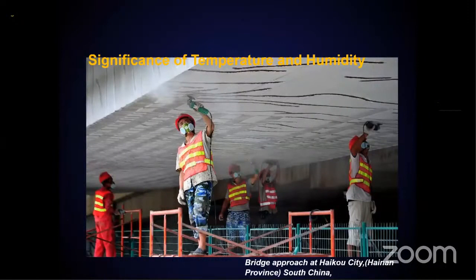And therefore, if you see, this is one of the bridges in China. It was built in almost 2013. And if you see, from the day it was built, a lot of cracks were formed. About 200 to 300 cracks were seen underneath the bridge, and they were all superficial cracks.